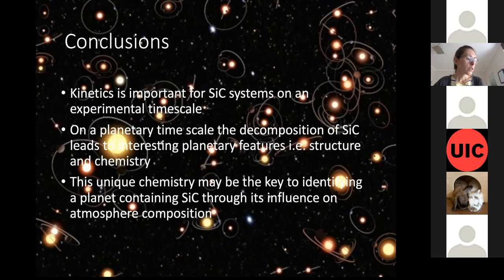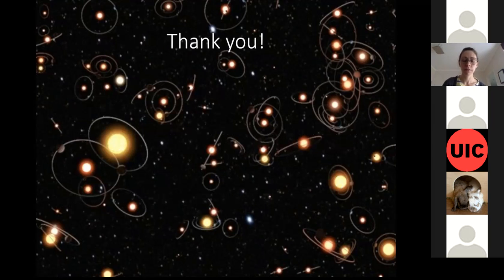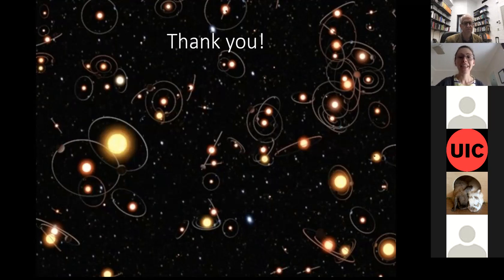So to conclude, kinetics is very important for silicon carbide systems, especially on an experimental timescale. On a planetary timescale, you will presumably be achieving equilibrium. And so things that we're observing, like the decomposition of silicon carbide and these high pressure transitions, would lead to interesting structure and interesting chemistry. Some of these unique chemistry fingerprints might be the key to identifying a planet containing silicon carbide. What we're finding is that this may be done through its influence on the atmosphere composition, particularly nitrogen. Thanks for inviting me.